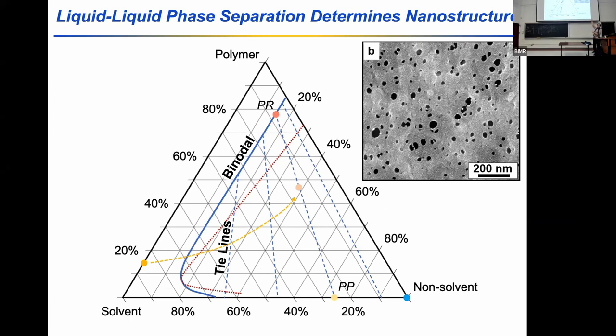The parts that appear bright in this SEM micrograph are the polymer-rich portion. They form the matrix of the membrane. And the parts that appear dark or black are the polymer-poor region. They form the porous structure of our membrane. And so this nanoporous structure, and the fact that we've got pores of a particular size, is why these membranes end up being used in filtration processes.